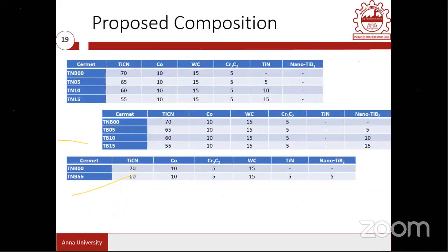So in that aspect, we have proposed nearly 6 compositions. The first composition is represented as TN, which means we have added titanium nitride. To represent this titanium nitride, we use TN05, and so on, that means 5%, 10%, 15%. The other compositions are the same. Here TiCN is taken, and cobalt is the binder material, tungsten carbide will assist the sinterability, Cr3C2 will improve the hardness value, and titanium nitride will also improve the hardness value. So what is the effect of this titanium nitride on the hardness and toughness value?